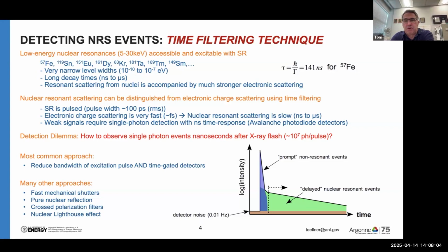Another aspect is the pulse is extremely strong. Typically in the case of beamline 3ID, in a 2 eV bandpass after a high heat load monochromator, for example, we have 10 to the 7 photons in one pulse. And that pulse, like I mentioned, is a couple hundred picoseconds long. So that's a very strong excitation pulse. That's too much for fast nanosecond resolved timing detectors to handle. So that needs to be reduced in some efficient way without limiting our nuclear resonance scattering events.